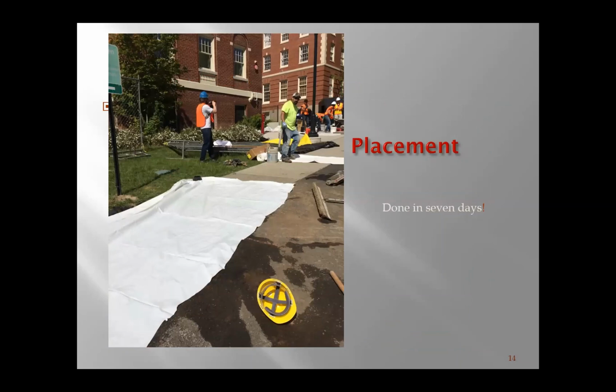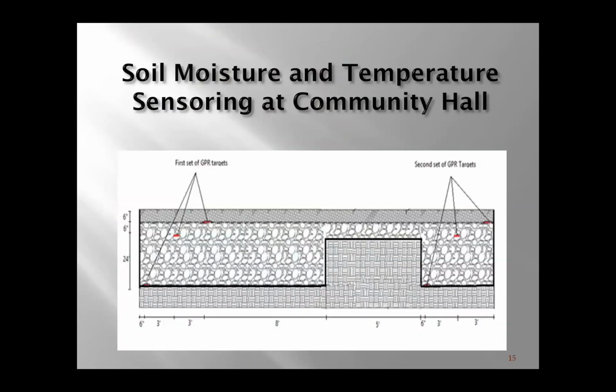So what did we find out from this sidewalk? This is an elevation view of it, where to the right you can see the upper bed and the dam, and then the lower bed, so you can see it's an aggregate bed with a pervious concrete layer on the top. They happen to have a 6-inch thick pervious concrete layer, which is pretty thick for a sidewalk, but it just so happens that in Pullman, Washington, their sidewalks are designed for various vehicles to ride on, for snow plowing and other reasons. So they use the same type of depth you might use for a parking lot. And then you can see there's a good 2.5 feet of aggregate storage bed. There's a lot of water to store.